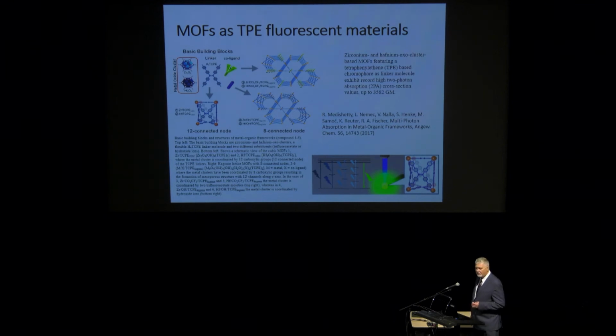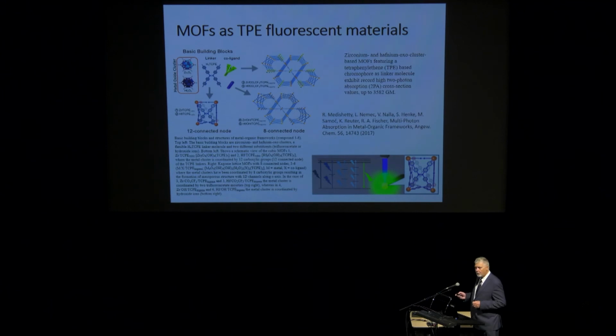That's an example. That's one of the first papers on nonlinear optical absorption and nonlinear optical absorption excited luminescence in MOFs. And in this case, it was possible to excite this material by 2-photon absorption, 3-photon absorption, 4-photon absorption, and in all cases, this efficiency of the excitation was high, was much higher than in the case of the ligand itself. So we did have this enhancement due to the aggregation of the ligands inside the metal-organic framework.